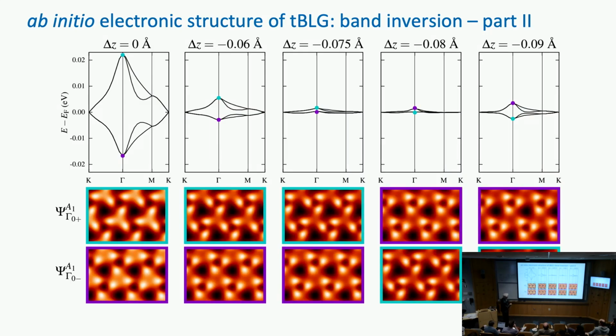And here are the wave functions to explain this. So here's the cyan wave function corresponding to this point, and it is the same here, and all of a sudden it's down here. So this is the same wave function, as you can easily tell visually inspecting this. And this is the same wave function, the purple one, which used to be here, and after compression it ends up here. So again, there's another switch in the character. Not only have the bands crossed along the K values, as I was showing you earlier, but now you have mixed what used to be electronic states above the Fermi level to hole states below the Fermi level. So there's an additional type of transition, topological, geometric type of transition that we are predicting.